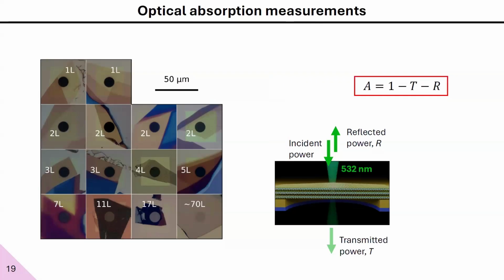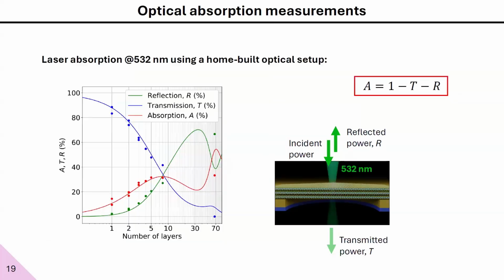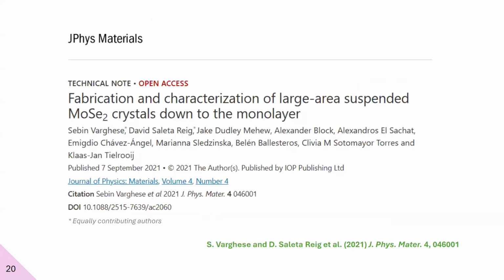Importantly, our samples enabled for the first time direct optical absorption measurements. Basically, we shine a laser, and we measure the transmitted and the reflected power to estimate the absorption of our samples. This is a prerequisite for our next set of experiments, where we study the in-plane thermal transport. These are our results. We see that the reflectivity increases monotonically from 2% at the monolayer to around 20% for 5 layers. And the absorption is about 10% for monolayer, going up to around 33% for thicker materials. We summarized our results in this technical note, which we published in 2021 in the Journal of Physics: Materials.